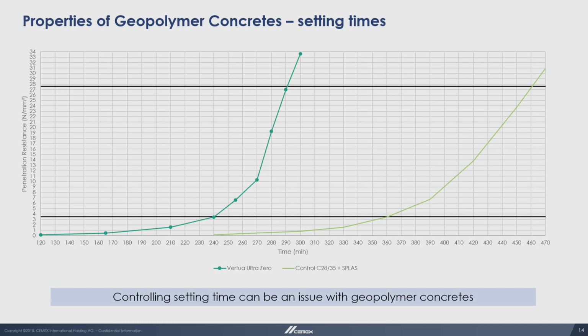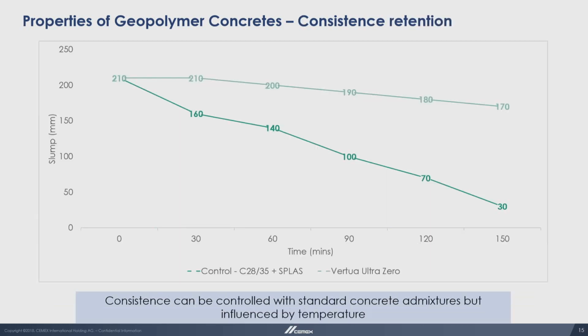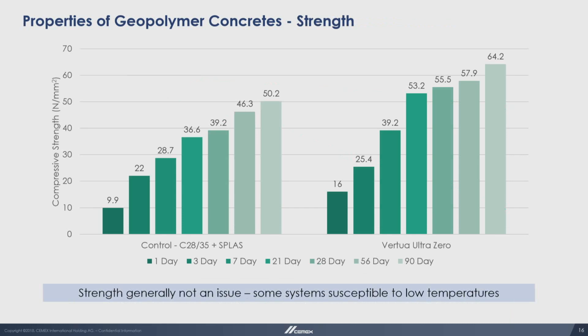Setting time, they do set quicker, which actually can be an advantage, but you can control it with admixtures. Consistence retention, this is comparing it to a more standard concrete. And again, these can be controlled with the right admixtures. If you didn't have any admixtures in, they have a tendency to lose consistence very quickly. Strength-wise, this is a straightforward comparison. 50, 60 megapascals quite easily to achieve. There are some formulations on the market that would claim to go up to 80, 90 megapascals. So for most applications, these types of concretes can deliver the strength that most people are looking for.